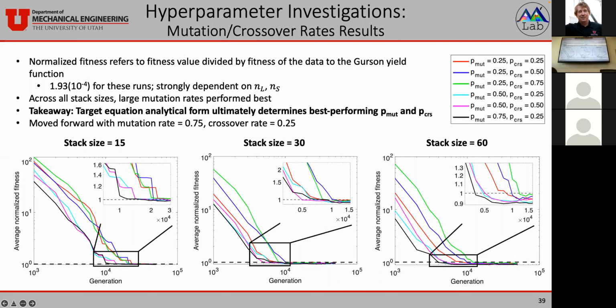Another thing to point out, we see larger stack sizes in this zoomed in image have a higher tendency to overfit. This is to be expected. The complexity of the yield function is 11. So going to 60, we do expect to see some overfitting like we did with the unit circle test problem. The takeaway from this slide for using GPSR in practice is that the target equation analytical form ultimately determines the best performing mutation and crossover rates. We don't see much variation in the performance, so these don't seem to have a large effect on the performance of GPSR. But we did see that large mutation rates performed best, so that's what we moved forward with.